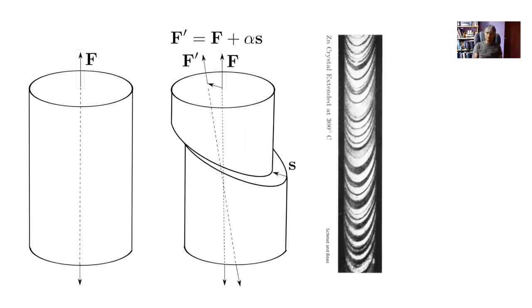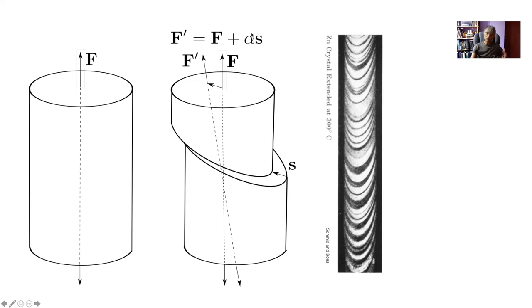In the single crystal with a force applied along the vertical axis, the resolved component along the slip direction on the slip plane creates a step in the direction of the unit vector S. The top half is displaced with respect to the bottom, causing the force axis to rotate to a new position F', where F' is the sum of F and the amount of shear applied times the unit vector S.